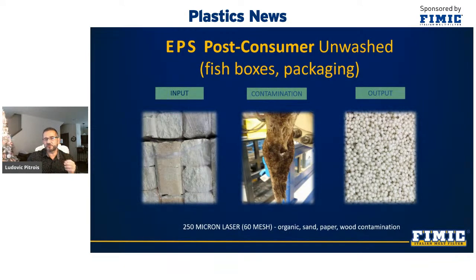Other example of circular economy and material that could be recycled. This image corresponds to the expanded post-consumer polystyrene filtered with a screen of 250 micron, equivalent to 60 mesh. This material is very special and difficult. Very often, it cannot be washed because of its very light and its electrostatic nature. Then, contamination level can be very important. A finer filtration can also be applied to produce micropellets in case of the application that requires it.